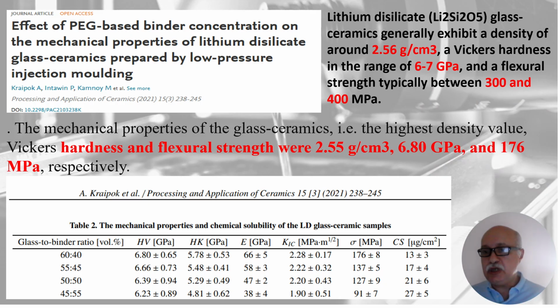Glass ceramics generally exhibit a density of 2.5, Vickers hardness of 6 to 7 gigapascal, and fracture strength typically between 300 and 400 megapascal. And in this research, with decreasing the resin portion and increasing the glass ratio, they could only reach about 170 megapascal fracture strength.